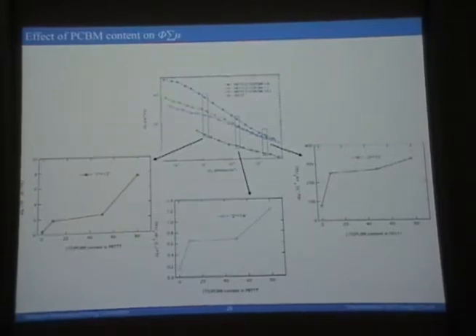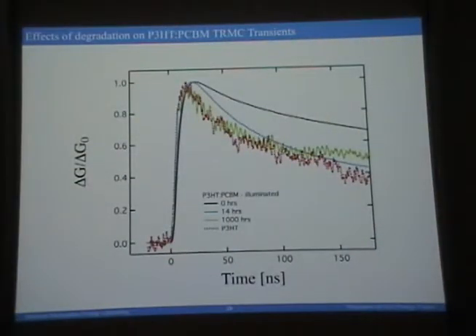You know, so MEH-PPV PCBM devices require a 4-to-1 ratio. P3HT PCBM only needs 1-to-1. So which is the best one to use? Do you need a lot of PCBM, or do you need to stick to a 50-50 ratio? So it's an interesting point. You need the PCBMs to cluster very quickly, and they do so in P3HT. Two more slides. This is where we do degradation studies with NREL, the device people. Unfortunately, that's where they get most of their money from these days.